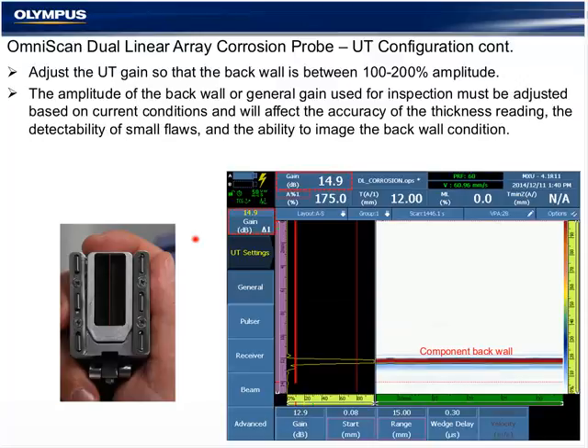Adjusting the UT gain so that the back wall is between 100 and 200% amplitude will ensure that you minimize lost data points as a result of uneven surfaces and non-parallel orientation of the back wall, and it will give us a good reading.